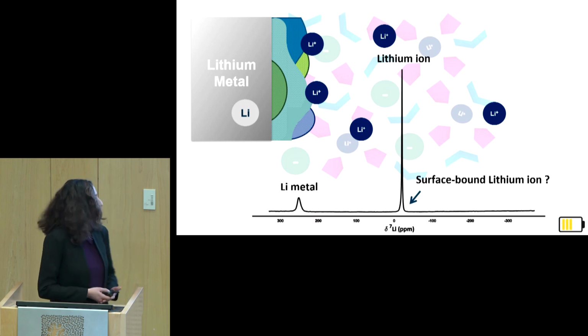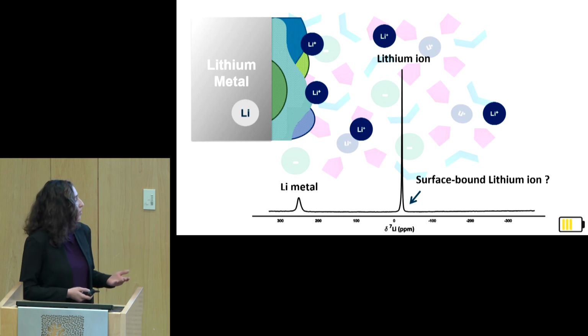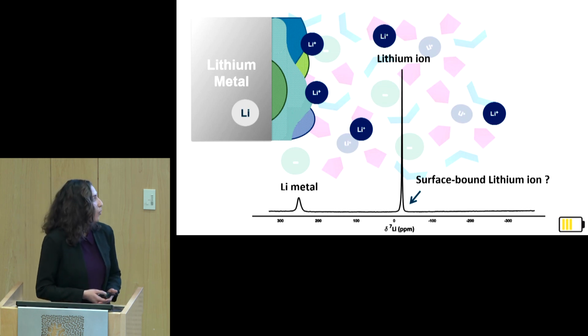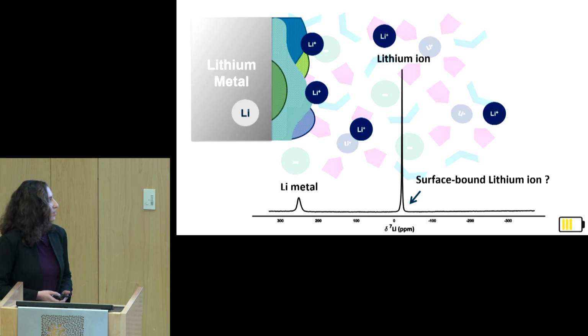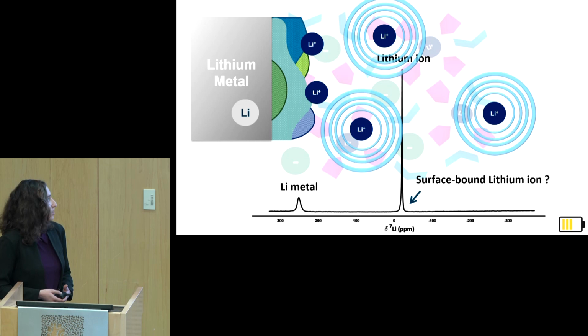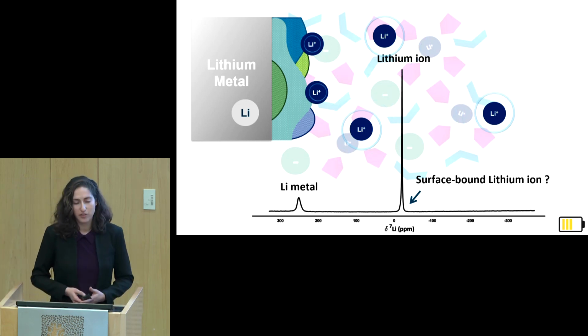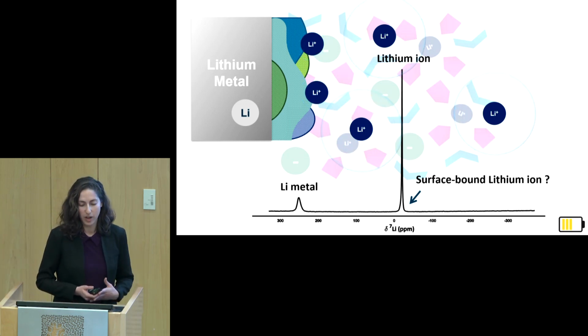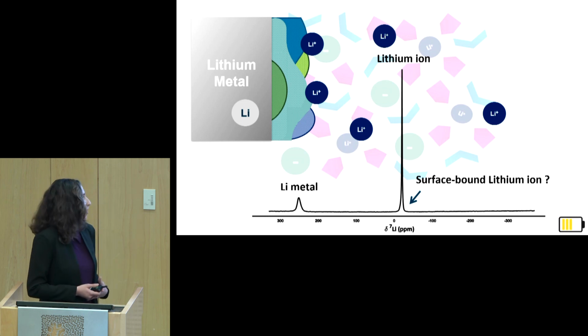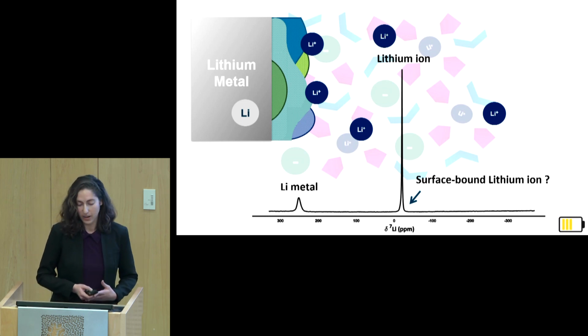But as you can clearly see, when we measure, we only have two peaks. One very sharp, intense peak for the lithium in the solution, the dissolved lithium, and one smaller peak for the lithium metal. But the peak for the surface-bound lithium is missing. There are many reasons for this, including the diverse surface layer, which has many different chemical environments, the quickly disappearing signal of the surface-bound lithium, and the very small surface area.